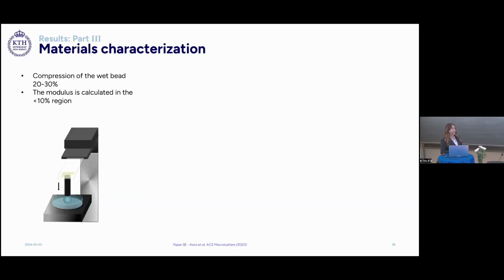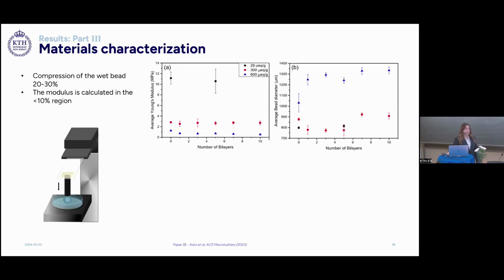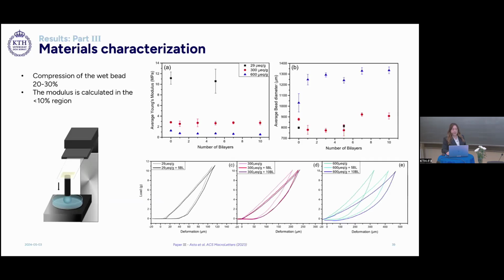Now, to study the effect of these adsorbed layers on the surface on the elastic properties of the gel beads, we performed a compression test of the gel bead using a modified version of the contact adhesion tester, where we compressed the beads to 20 to 30%, and the modulus is measured in the first 10% region. We can see that the elastic properties are not significantly affected by the adsorption of the LBLs on the surface. However, we can see that the highest charged beads are the most deformable.